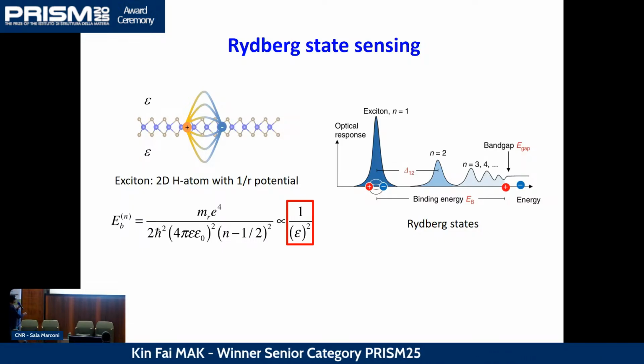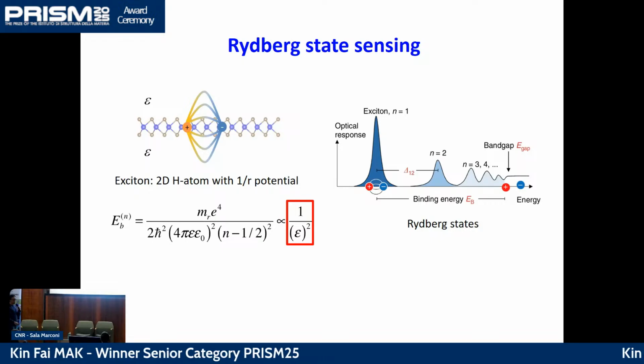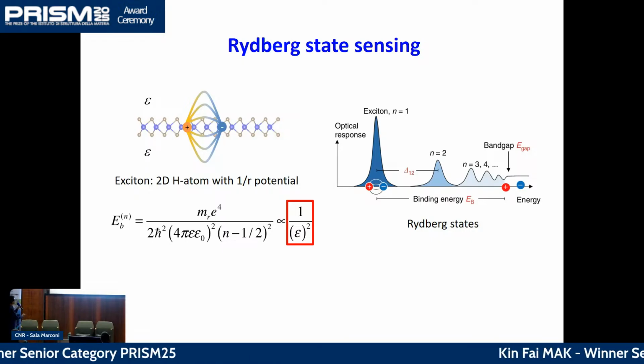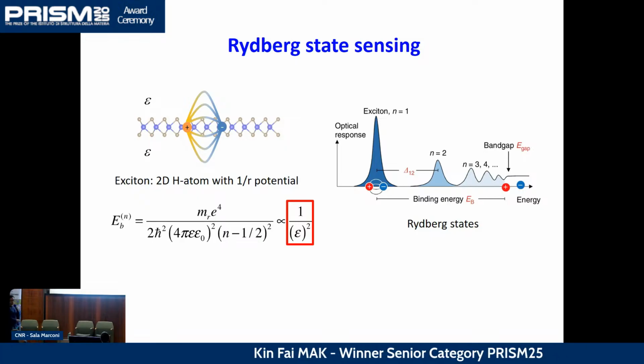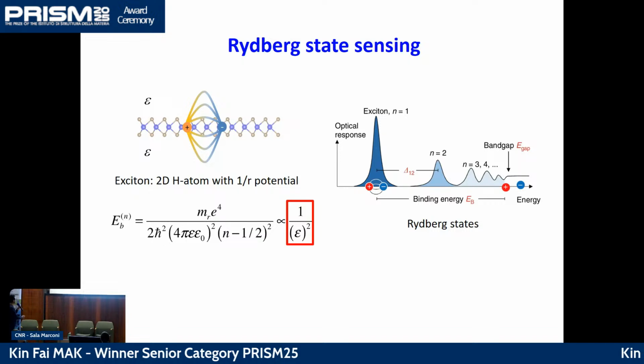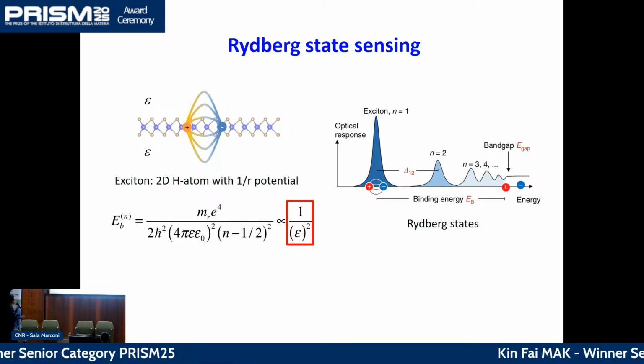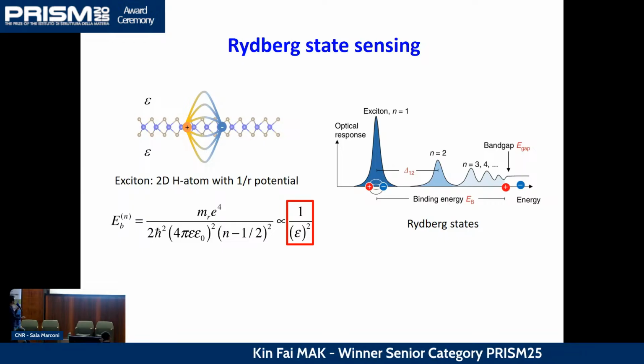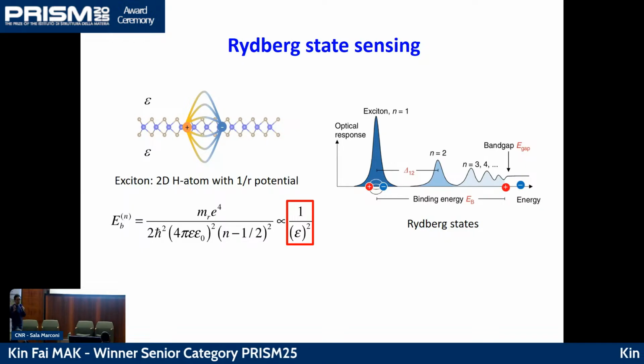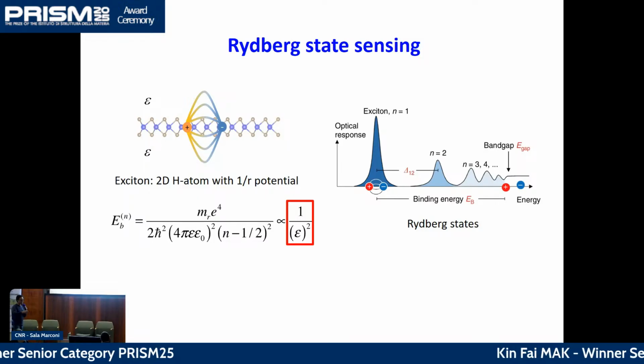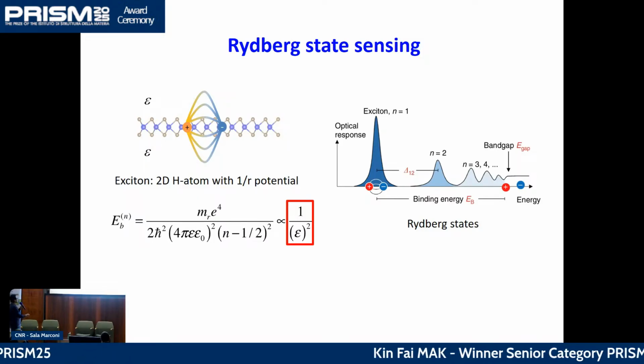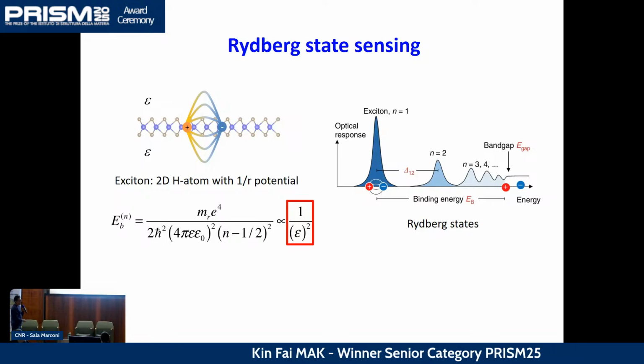And these are the electrostatic field lines that bind the electron and hole pair together. And you can actually see that for these 2-dimensional excitons, most of the field lines responsible for binding actually live outside of the material, not inside. Okay, and this is the binding energy of the exciton. It's a long expression, but the important thing I want to point out is that the exciton binding energy is sensitive to the dielectric constant of the surrounding environment, because the electrostatic field lines live mostly outside of the plane.